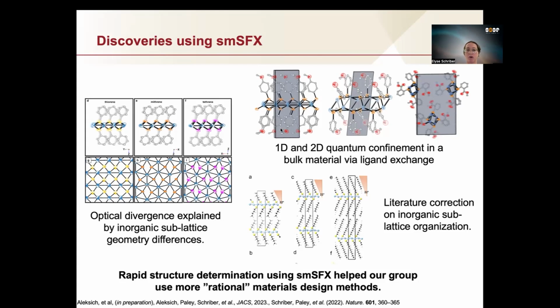As our methods have become more refined and our synthetic strategies have advanced, we've also been able to show that you can actually do ligand exchange that can change the 1D and 2D quantum confinement in bulk materials. So normally the inorganic sublattice acts as a 2D nanomaterial. So the electron wave function is quantumly confined to this inorganic sublattice. And we found that by doing ligand exchange, we can actually form almost inorganic nanowires in these 3D materials. And now we have one-dimensional quantum confinement. So a lot of really interesting science is being developed and discovered by way of using small molecule SFX.